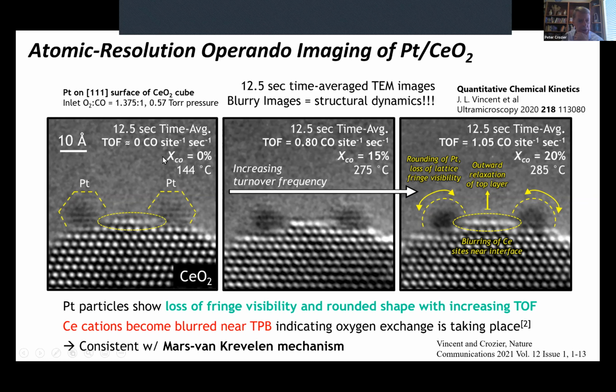And initially, the conversion of CO is 0 at 144 degrees. And as we increase the temperature, because we can measure kinetics quantitatively, we can determine what the conversion is, about 20%. And from quantitative chemical analysis, we can convert that conversion into turnover frequencies. So the turnover frequency is 0 at 144 degrees, and it's about 1 per site at 285 degrees. And what I want you to notice is the difference in the appearance of the catalyst when the catalyst is active and when the catalyst is not active.